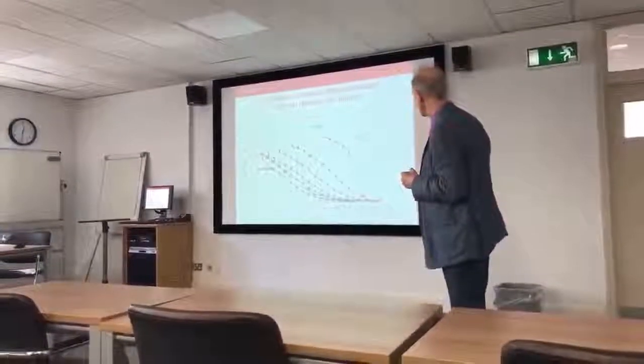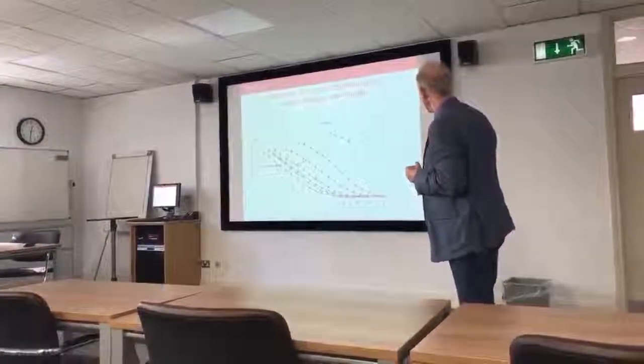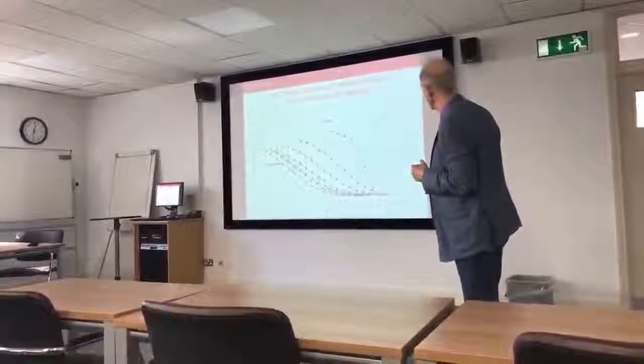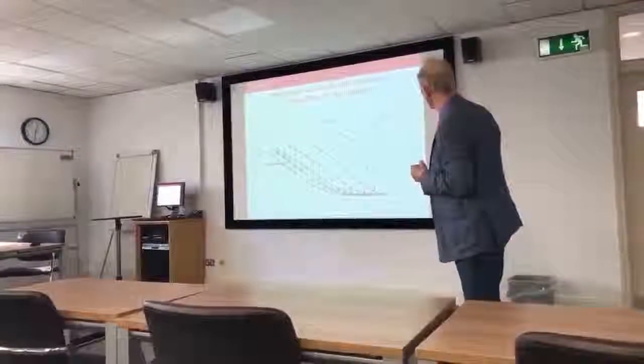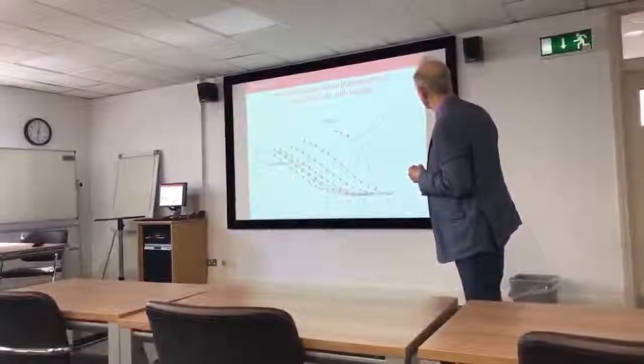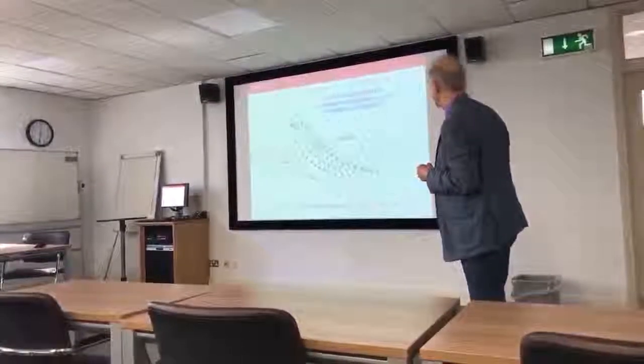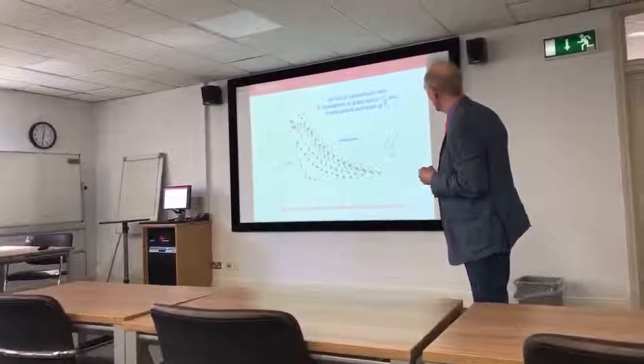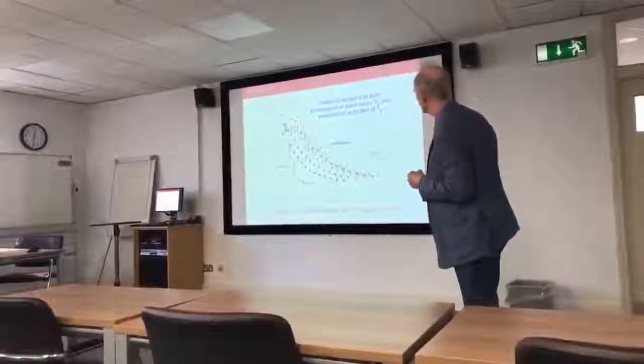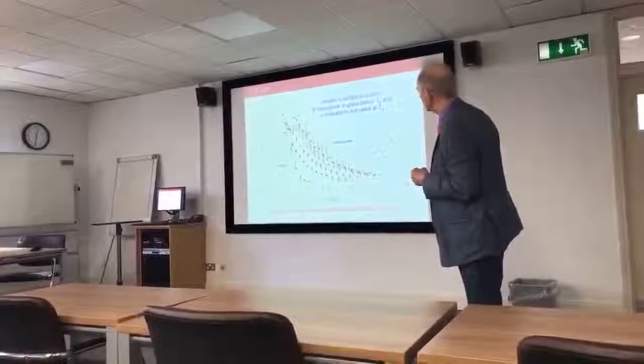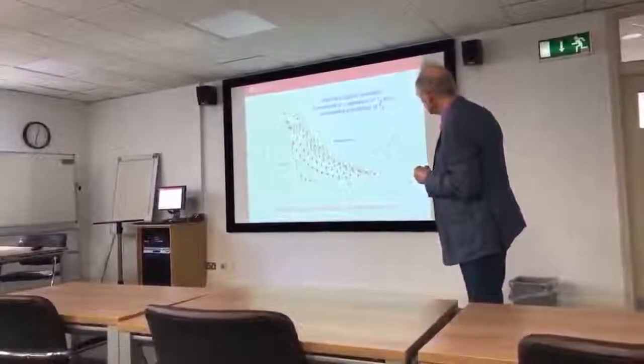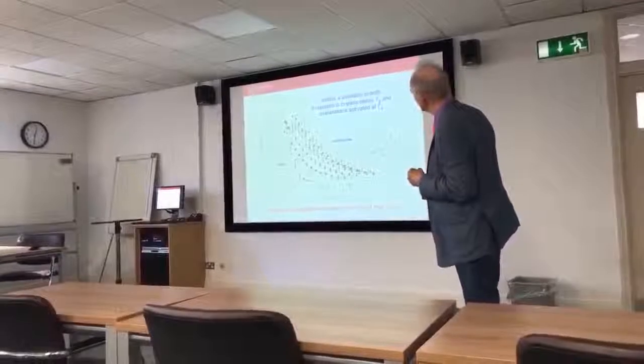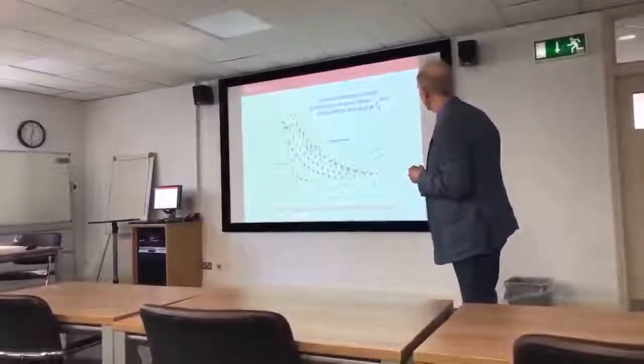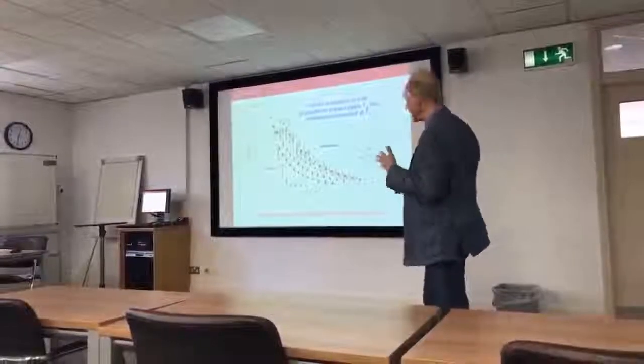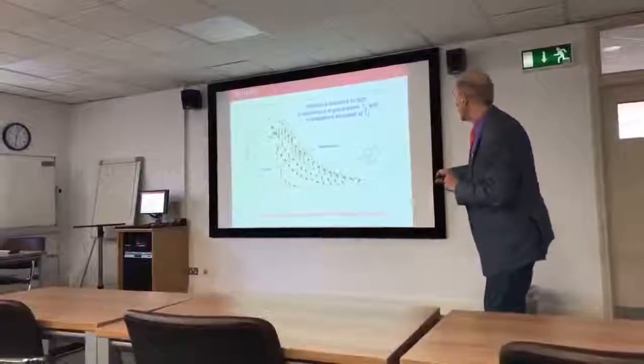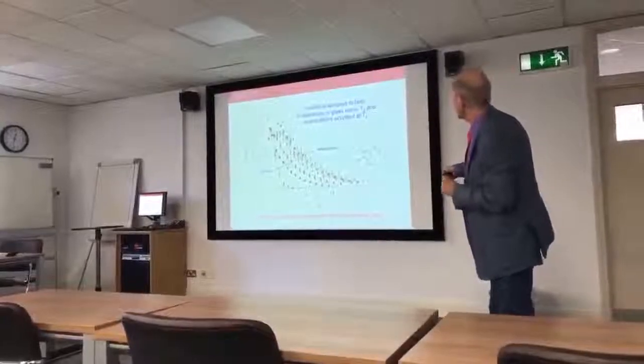This is a lifetime, again, T minus TG. You see the same sort of behavior. Glucose has a slightly different structure to the curve, but the rest of them are pretty much the same. And again, glucose at any T minus TG is much more rigid than the others. Do the same analysis, log KNR versus inverse TG, again normalized to the TG. Now I have to include values above the TG because KNR is still rising through the glass transition temperature into the melt. But again, you see essentially the same behavior. And that is that as you go to a more complicated sugar, the dynamics goes up.